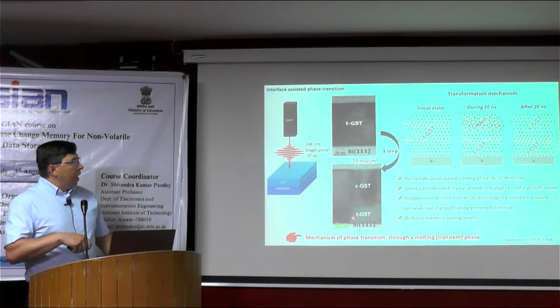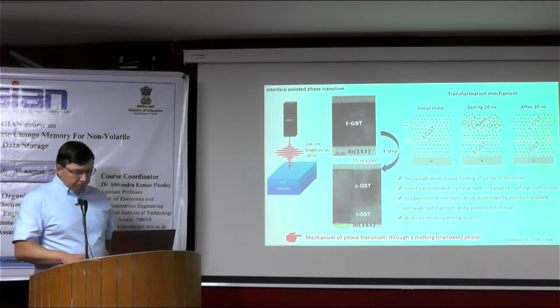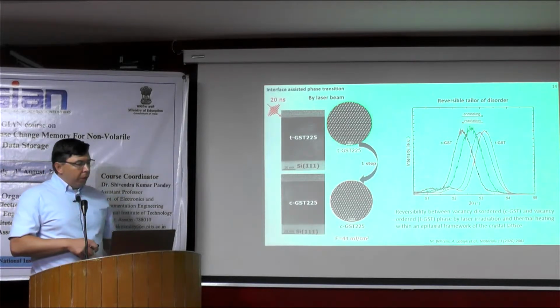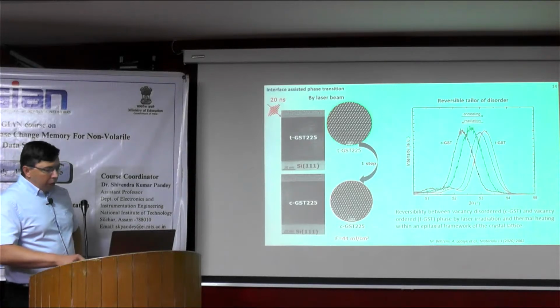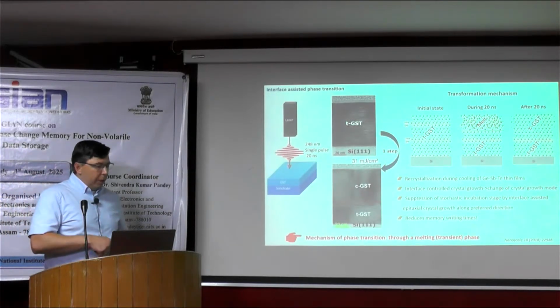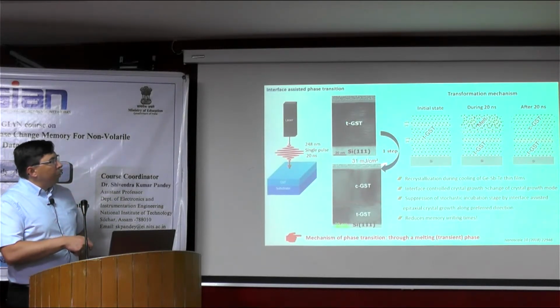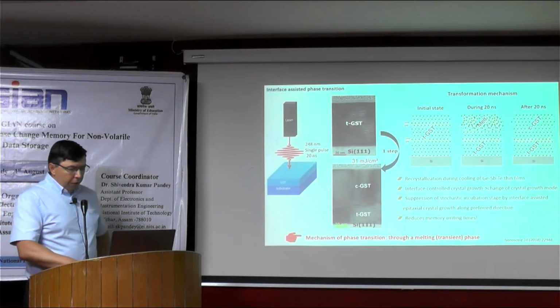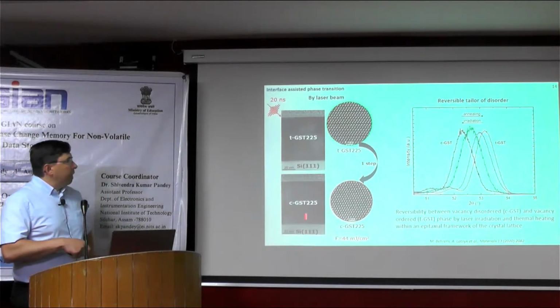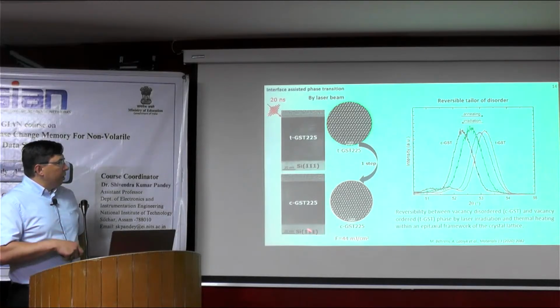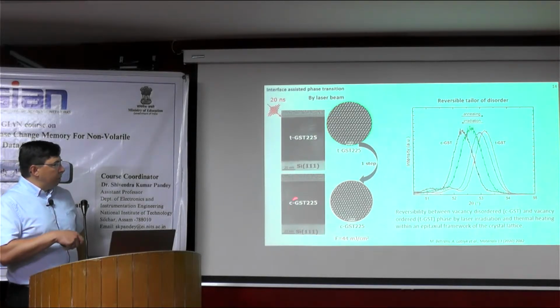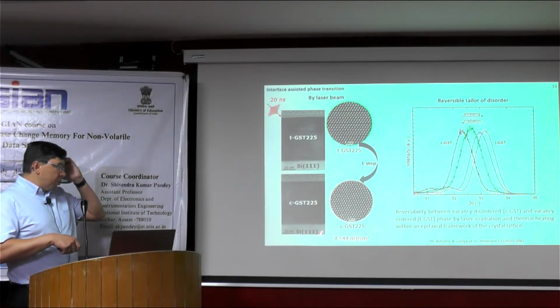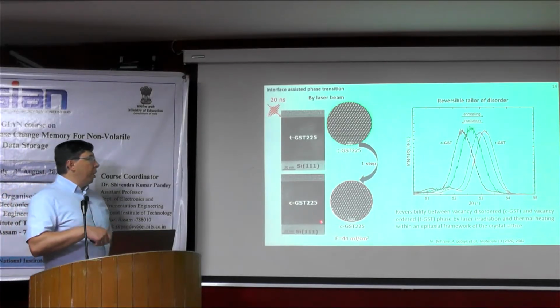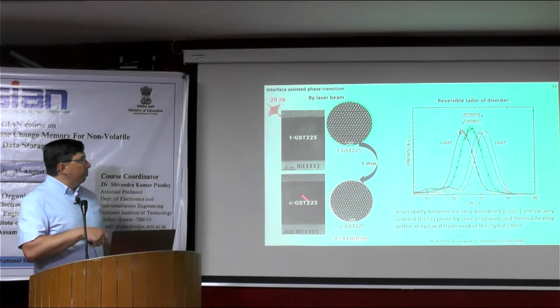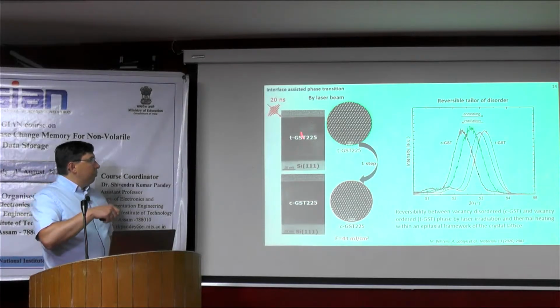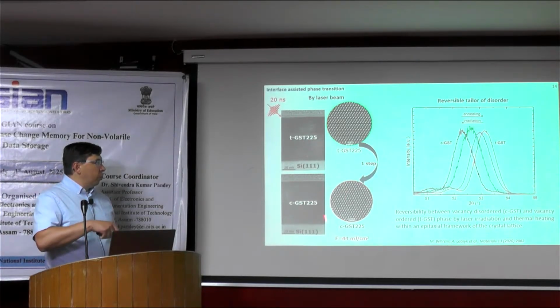So from a high amount to a low amount. Here we can show this: in this case the fluence of the laser was 31 millijoule per square centimeter, and then if we increase it, we can go completely to the cubic phase, CGST. So here they increase the fluence of the laser, but again this is the melt quench process. We first transform the phase to the melt, and then it recrystallizes into the cubic phase.